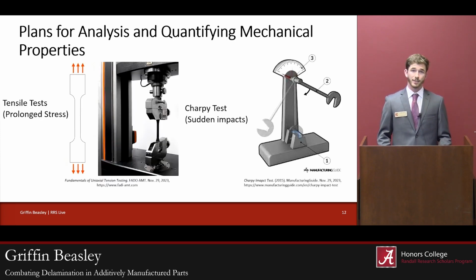For mechanical property testing, we intend to conduct two main tests, and those are the tensile test and the Charpy impact test. The tensile test applies an opposing force to two different sides of the test piece over a prolonged period of time. During this period of time, it measures the stress and the strain that the part experiences, and from this data can calculate yield strength, ultimate strength, and percent elongation. These values together can tell us how the part will perform under a prolonged stress.